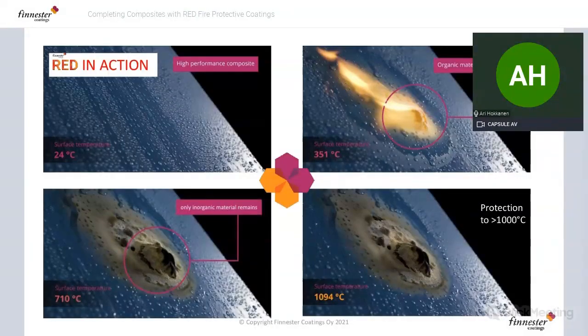So again, in a nutshell, standard composite at room temperature, Bunsen burner introduced to the surface, starts to increase the temperature rapidly, the organic materials burn away. This is completely okay. These are not incombustible systems, these are fire protected systems. And then ceramification has happened, and all the organics are gone. You can see this gray silvery area here, and that's a ceramic material. And then it stabilizes after 1,000 degrees and keeps the stable fire protection.